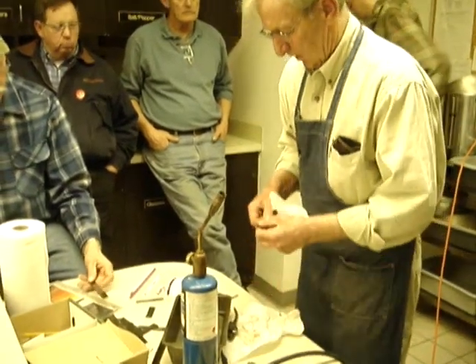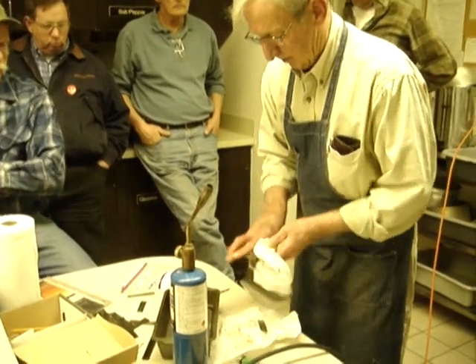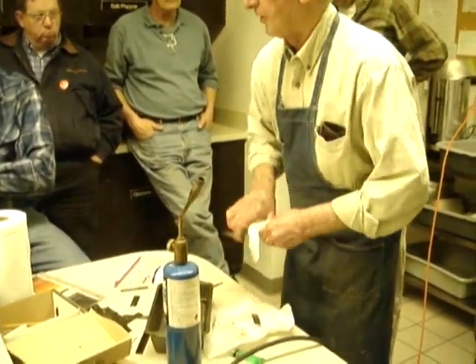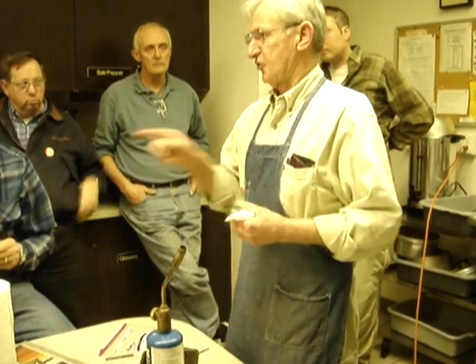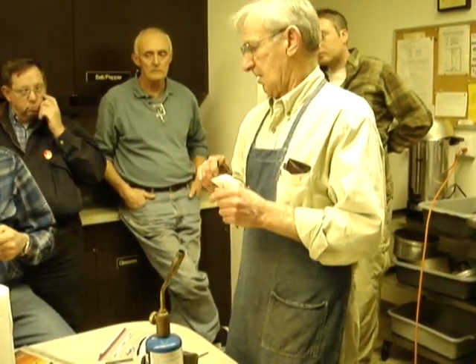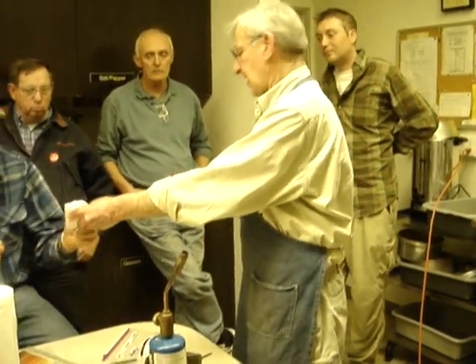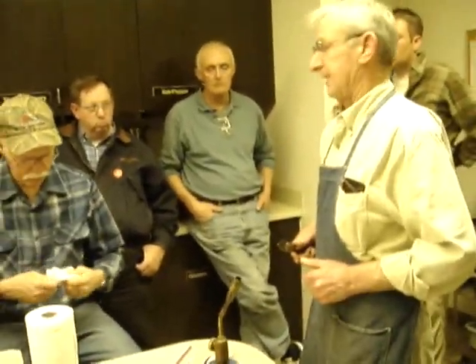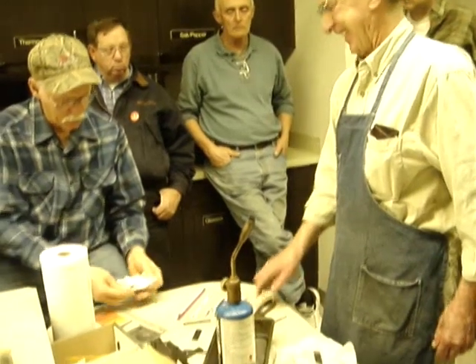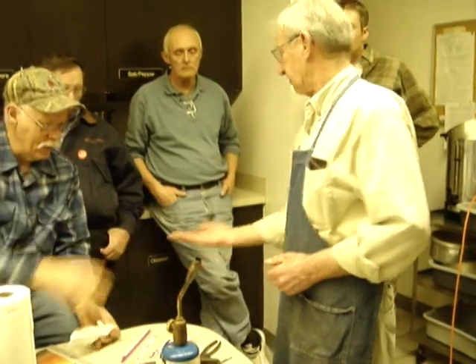So really what you want to do is heat treat it and bring it up to a point of hardness where it'll make a good knife for you. But that has to be annealed. That is way too hard, that edge will chip. You could probably break it by hand, huh? Try it. Wow, that is hard. Two places are broke. It doesn't even bend, it just breaks. It's glass hard. Make a little knife out of that.